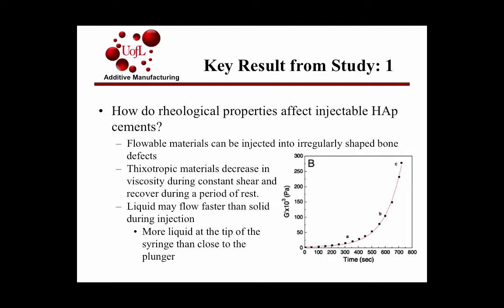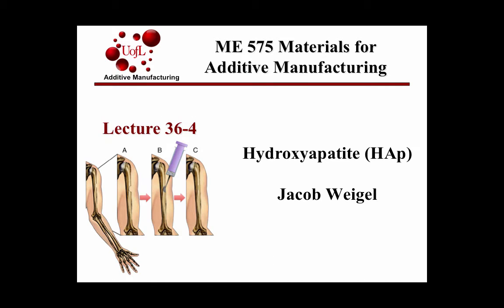All right, so for the HAP cements, which are the injectable, as you saw in the previous slide, these typically go in a syringe. The flowable materials can be injected into the irregularly shaped defects in the bone. So if you were in an accident or something, you wouldn't have a normally shaped defect. It would need to be something really custom designed to proliferate that bone growth. So with a flowable material, you can inject it in, and as you saw in this first picture, they take that syringe, put it into that hole, and then as it sits there, it hardens and promotes bone growth, and eventually it degrades and natural bone will replace it.